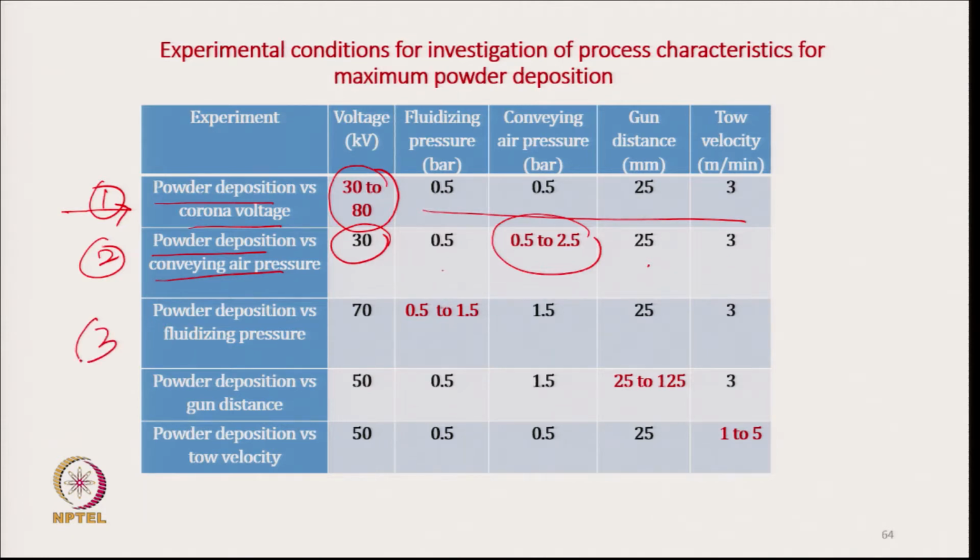In the third experiment, we changed the fluidizing pressure from 0.5 to 1.5 bar with the voltage kept at 70 kilovolt, and also other parameters were kept constant.